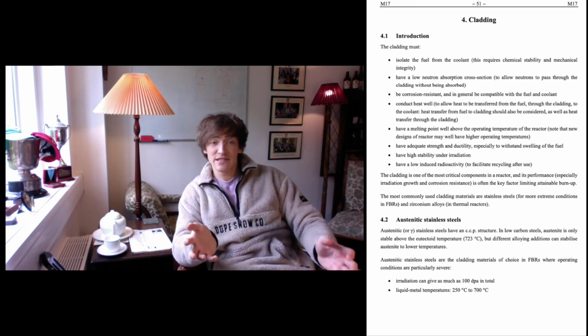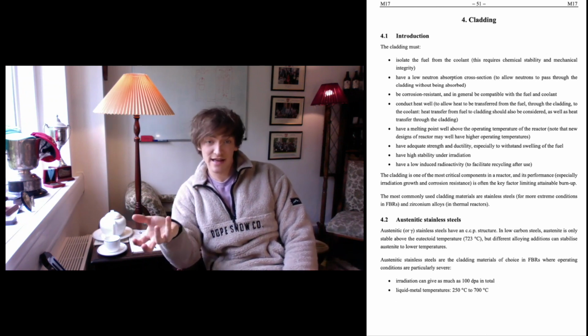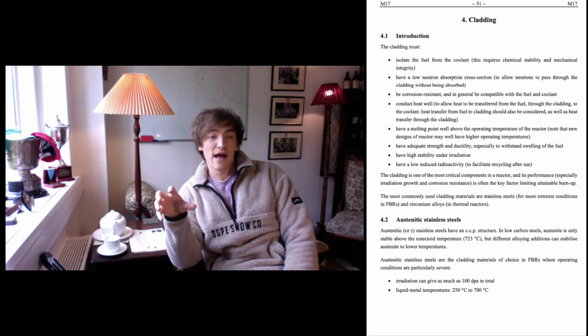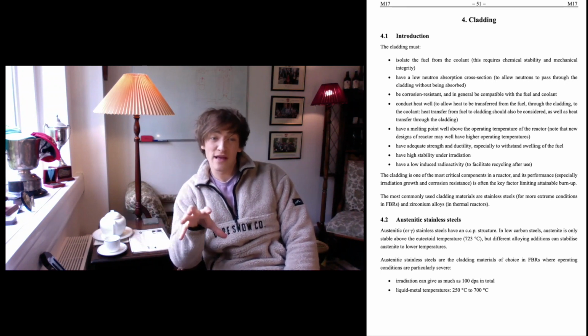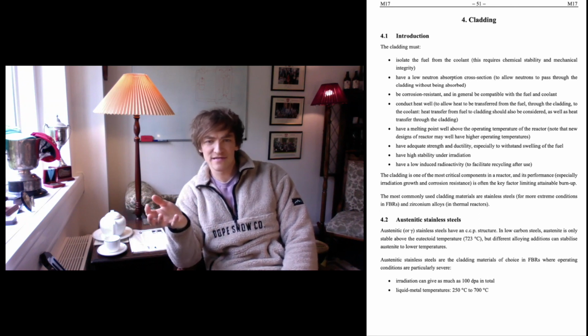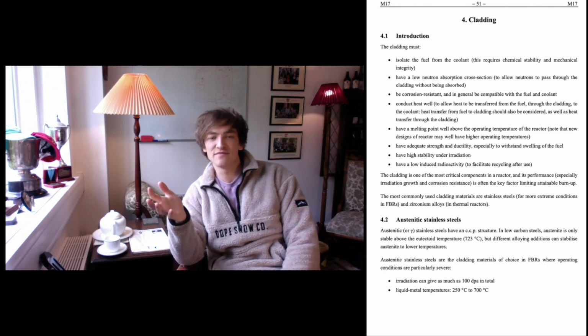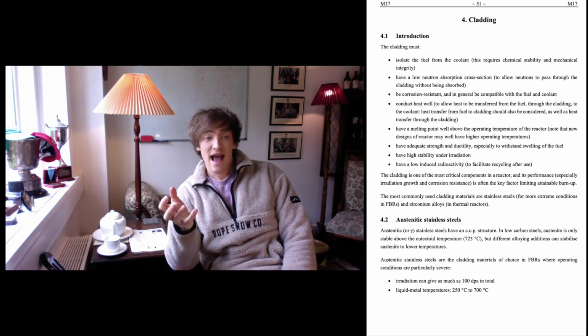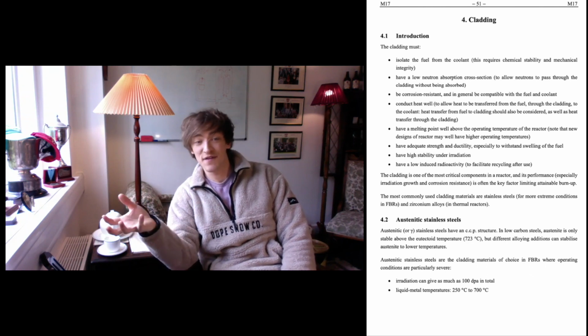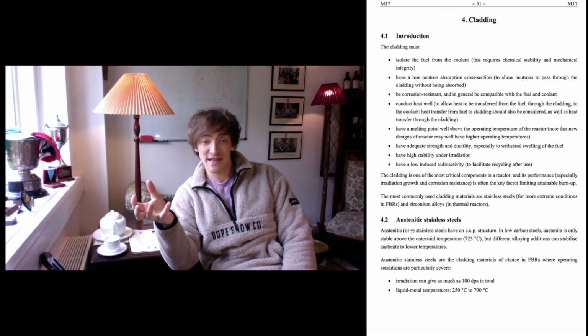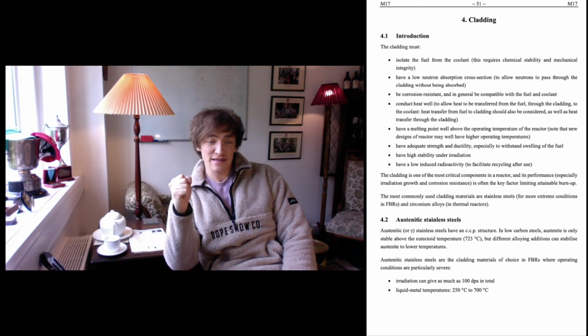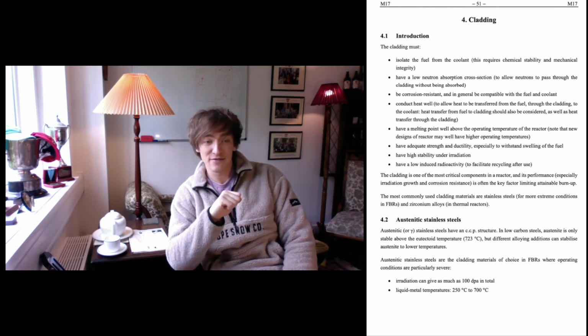Austenitic stainless steels are the cladding materials of choice for fast breeder reactors. Remember, the ones that use fast neutrons and breed their own fuel, where the operating conditions are particularly severe, where you're going to get total damage accumulating to up to about 100 displacements per atom. And you've got liquid metal coolants in those reactors, and they range from 250 to 700 degrees Celsius. So a real challenging environment to have a stable, reliable cladding to work from.